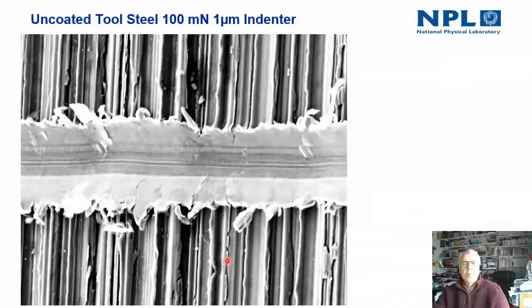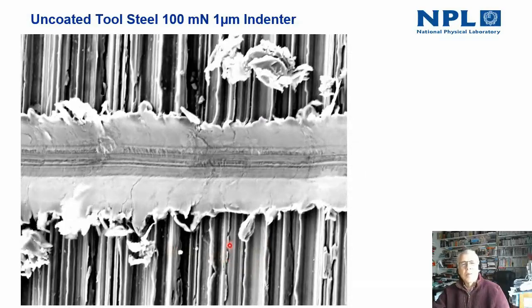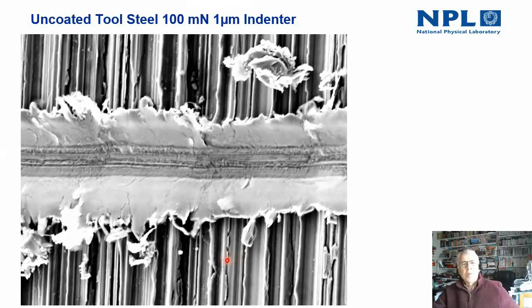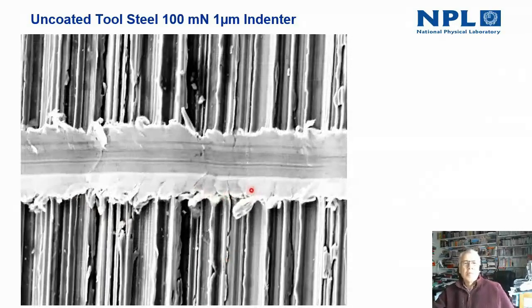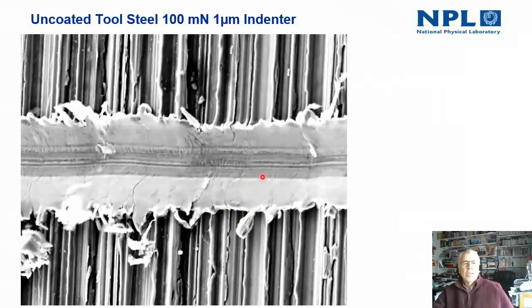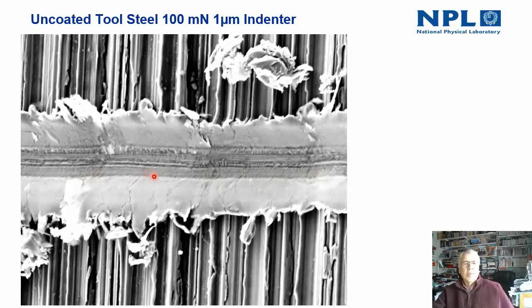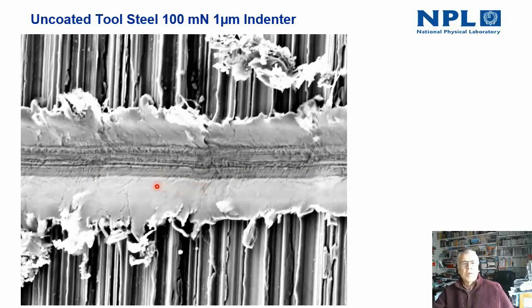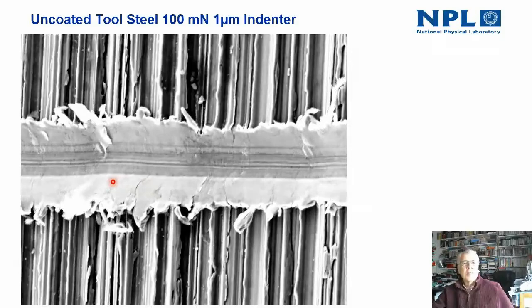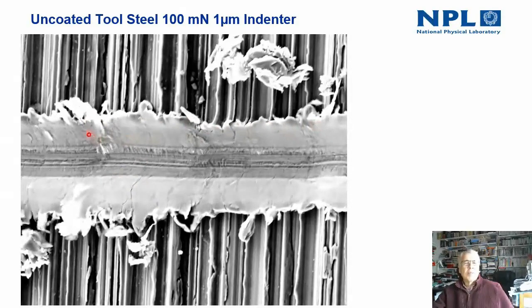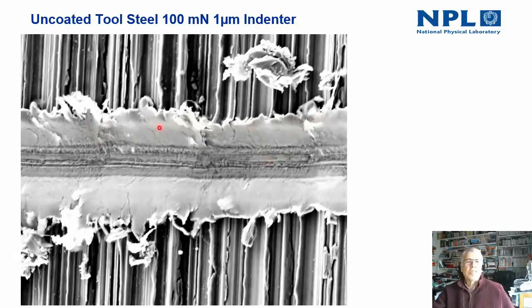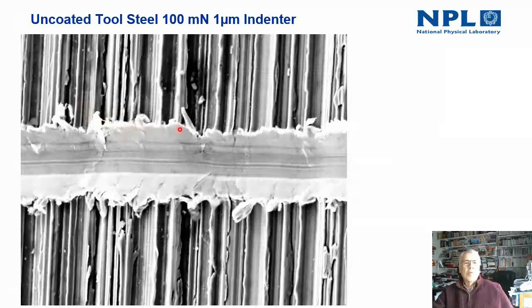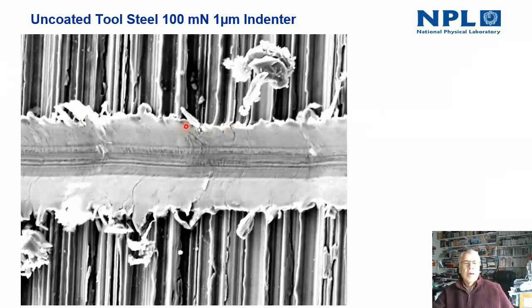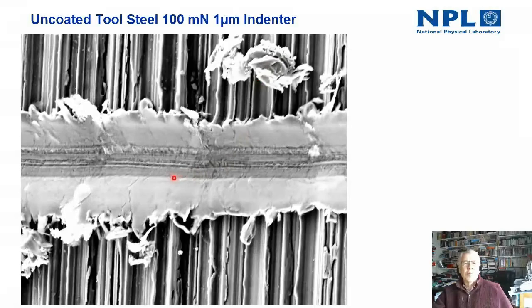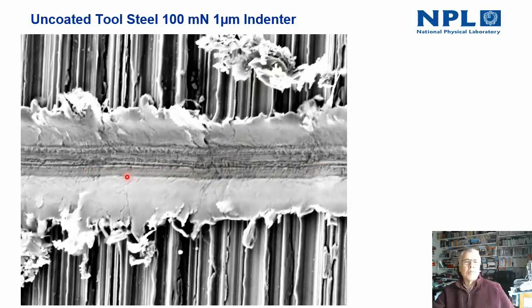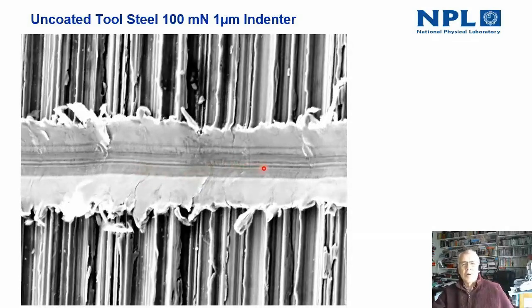And turning to coated materials, in fact, this first sample is an uncoated tool steel. It's rough. It's a ground surface, and you can see the development of the scratch here. Initially, the scratch is deepest where the surface is high and lower where the grooves occur, but eventually it covers the whole surface. You can see how material is being pushed out to the sides of the scratch, and you can see how chips are formed by the material removal process, and you can see one of them in particular there. It's also interesting to note how the microstructure of the material is changing in the base of the scratch.